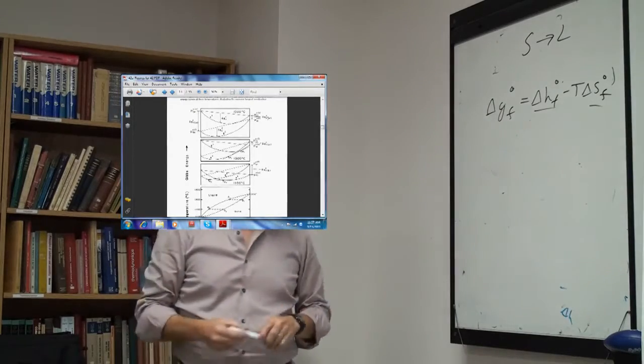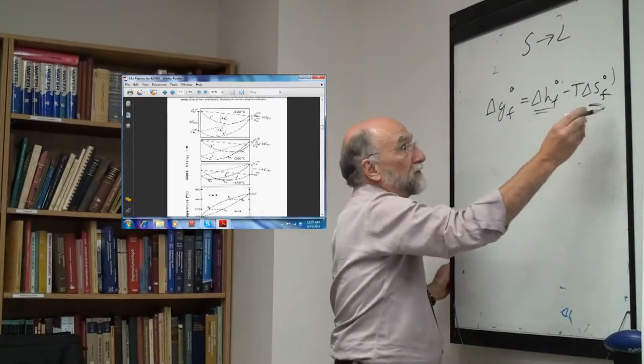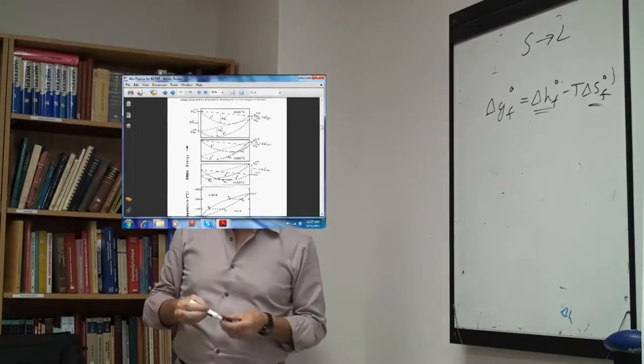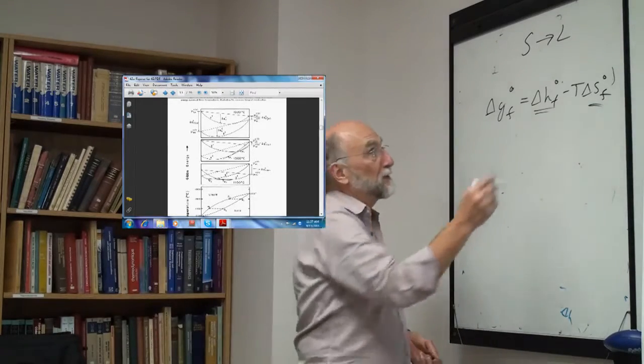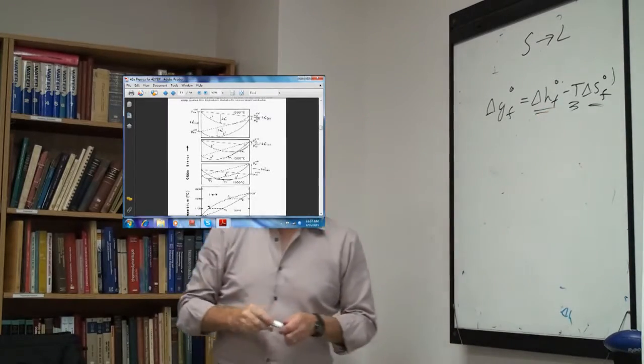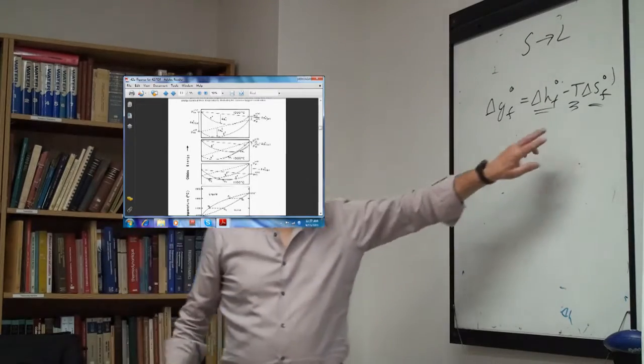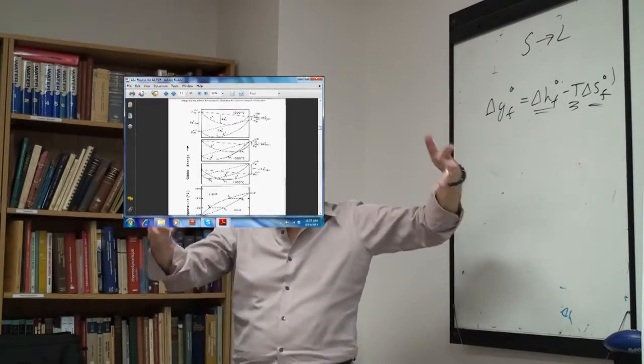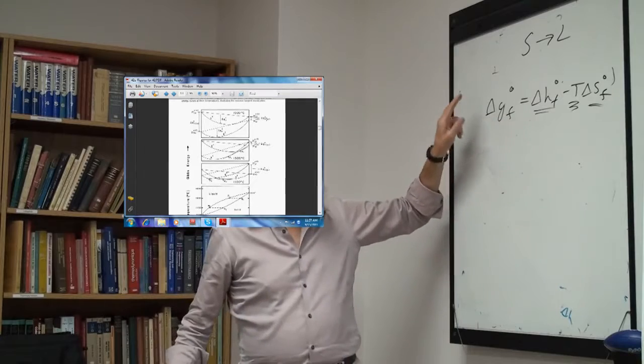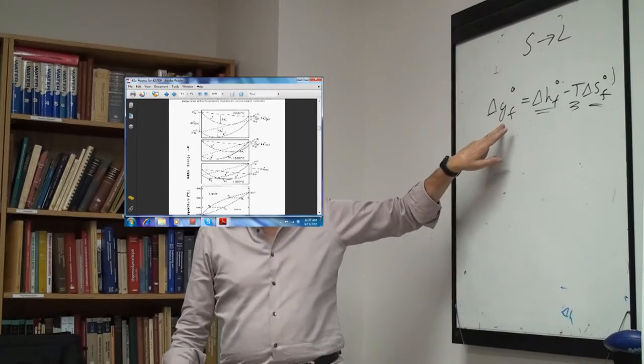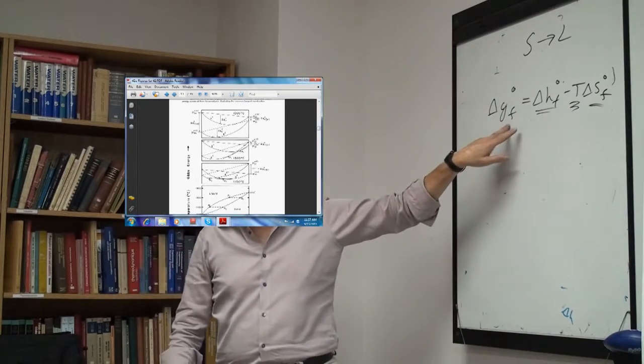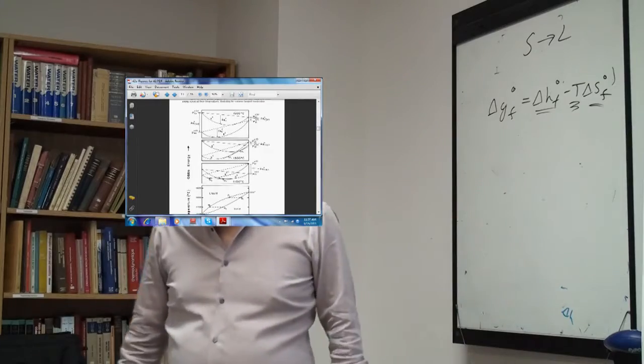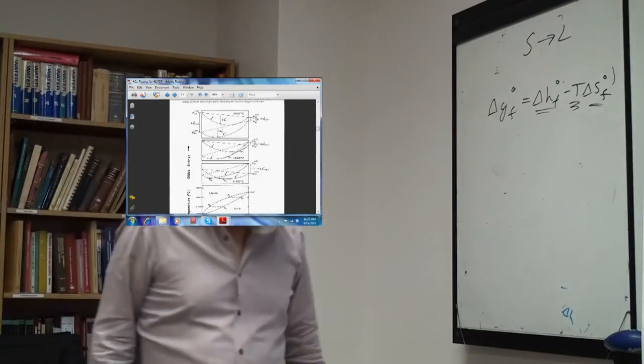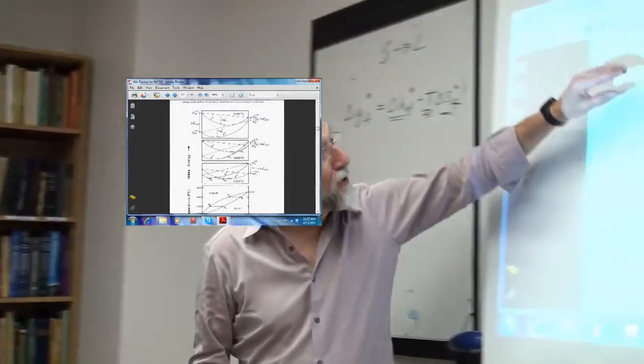But as you lower the temperature, yes, the heat and entropy of fusion change by the integral of delta Cp dT terms, but the most important thing is the T here. So as you lower the temperature, this term becomes less important, which tends to stabilize the solid. When you reach the melting point, the two terms are equal, and delta G of fusion is equal to 0, and below the melting point this becomes positive.